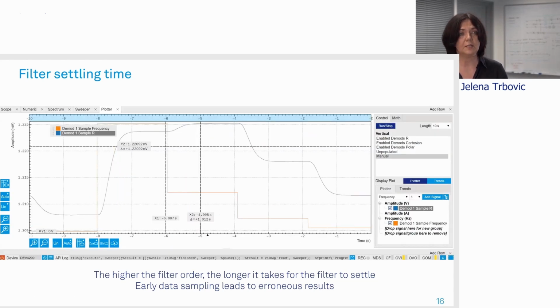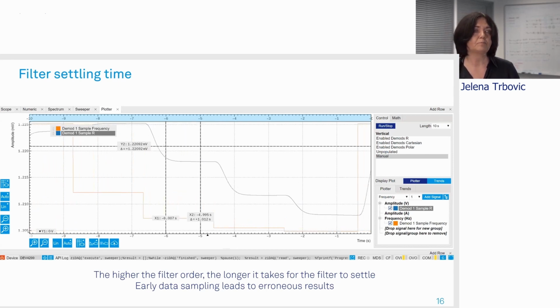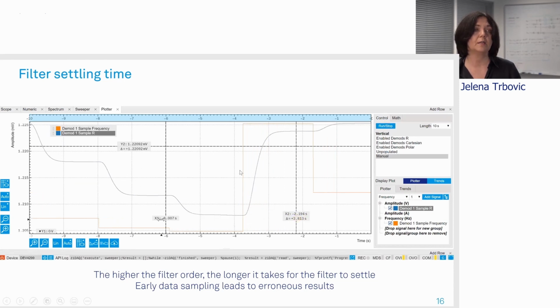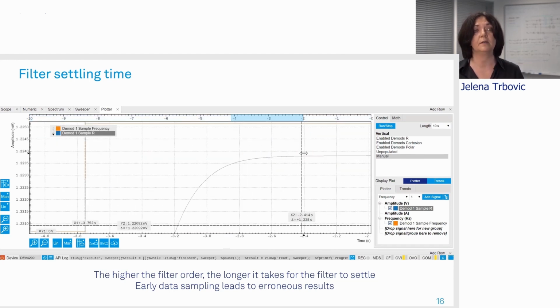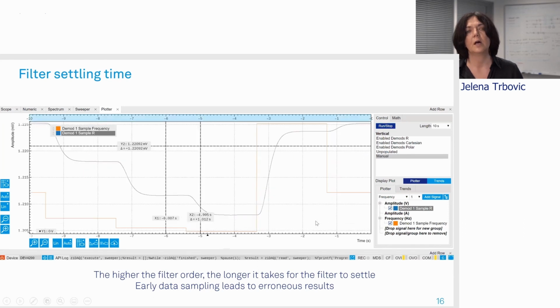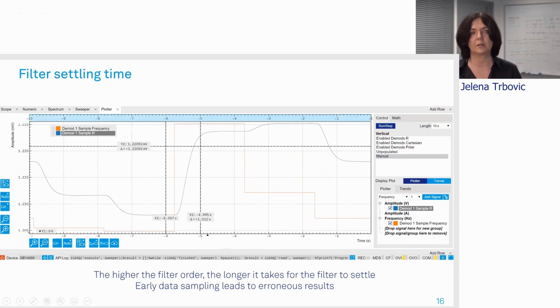And one way to see this is in this plotter, a little movie where we can look at the data, which are blue here, against this orange external parameter that we change, which you can understand as, let's say, magnetic fields that we need to sweep in the VSM measurements. And you see that for this 100 millisecond time constant, we need to wait more than 1 second for the signal to settle. So we need to be ready to perform these measurements.